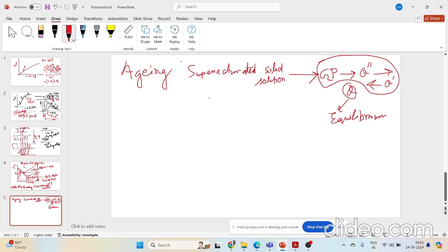Because the copper atom, you are mixing copper atom with aluminum, right? Because the copper atom is smaller than your aluminum atom in diameter, and your GP zones, those are supersaturated, right? Those zones are richer in copper than the solid solution. Then what will happen? Whatever your crystal lattice is having, the crystal lattice will be strained around your GP zone.